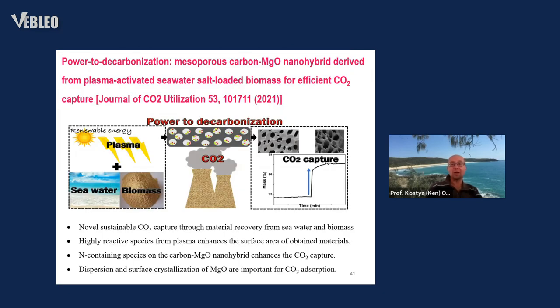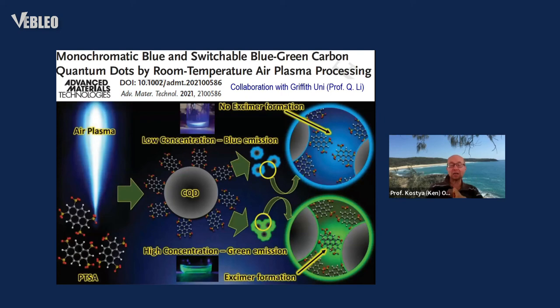As a further example, we can produce carbon particles that can later be used to test the water against contaminants. One viable way to do that is to customize the optical emission generated by the plasma-produced carbon quantum dots so that they emit light in a certain range. For example, here we produce carbon particles using plasma directly discharged on water containing some carbon precursors, so that some particles produce blue light and some produce green light. But we also produce some particles that are bifunctional, which can be excited in two frequency ranges, in blue and green.